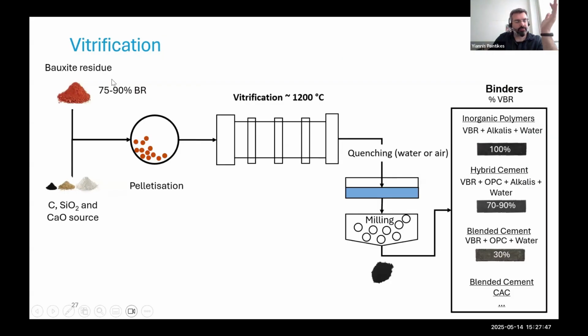In this case, you take, let's say, anything from 75 to 90% bauxite residue. You add easy things, silica and calcium. So I'm not talking about fancy fluxes, maybe some carbon. You will need some carbon, depending on how you do the process, because you want to convert that into a non-ferrous metallurgy slag. You want to go to the fayalitic region that is melting around 1200 degrees, depending on the exact chemistry, and use that as an SCM. So you pelletize, you vitrify, then you quench, and then you do the milling, and then you have a fine black powder.